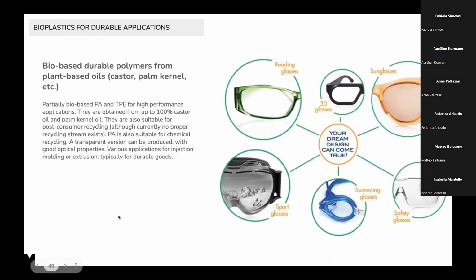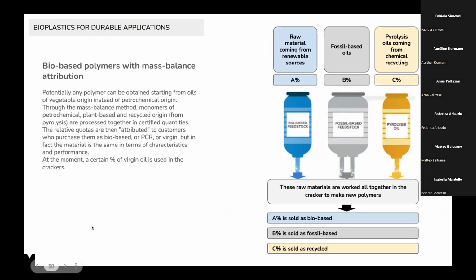Then we have bio-based durable polymers, typically polyamides or TPE or blends from plant-based oils, from castor oil, palm kernel oils, and other plant-based oils. And these are, again, completely durable, non-biodegradable, more resistant than cellulose acetate, and available and used also for very, let's say, demanding applications like eyewear frames, even ski boots. So with also a very good temperature resistance from very hot to very cold. So high-performing bio-based polymers.